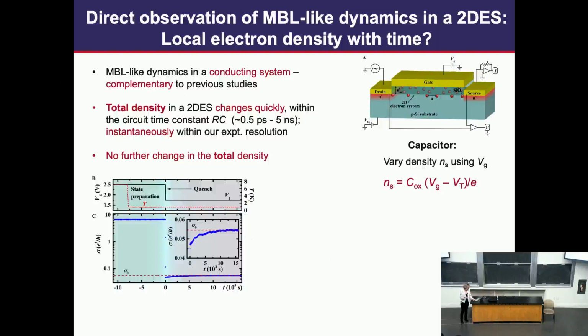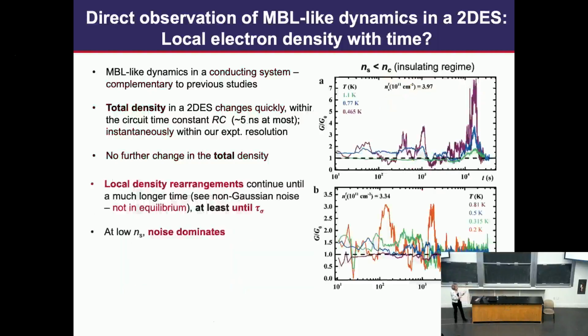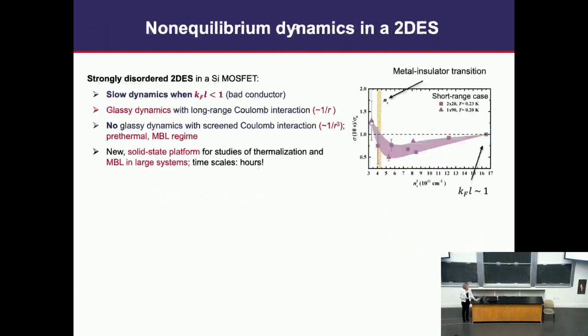There will be large noise. And indeed, these are examples of the data. You should never let data like this discourage you. In the insulating regime, everything is dominated by this huge noise. So this is consistent with the existence of local density rearrangements, but in this kind of device, we cannot probe this locally. We do not have other probes because of the gate, but it would be ideal to have some local probe like STM to see what happens with the density locally.